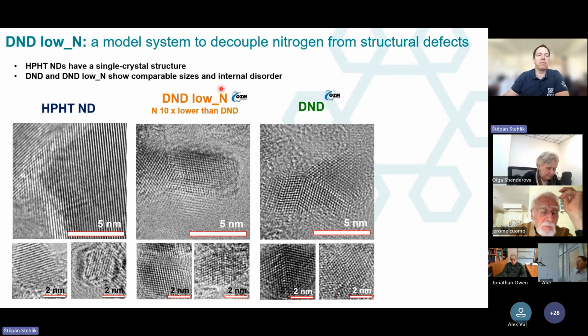It is the DND sample, but with a low nitrogen content. So it has about 10 times lower nitrogen content than the classical DNDs, which were also provided by them. So these are made from the TNT/RDX mixture, like typically. And we also involved the single crystalline HPHT nanodiamonds as a monocrystalline reference. So these are the newest results I'm going to show now, not yet published, but hopefully close to the acceptance of the paper. Okay, so when we did the TEM, we noticed that the internal structure is quite similar in these 2 DND samples, which was something we wanted. So the only parameter, hopefully, which is different here is the nitrogen content.